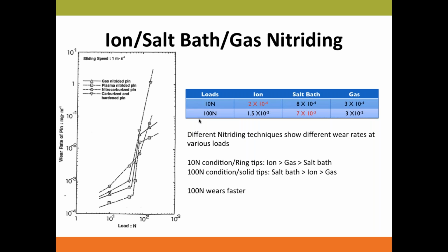But what's more interesting is when you put these three under wear test. On your left, it shows you the wear rate for different nitriding techniques under different loads. But I summarized the table for you, to make it easier to see. Let's say I pick two loads, 10 Newton and 100 Newton. If you have a 10 Newton load, ion performs the best. It will only lose about 2 times 10 to the negative 4 compared to 8 and the 3. But what's interesting is when you increase the load, the champion is different. Now when you increase the load, because salt bath has a more compact white layer, it's able to resist the wear better than the other two.